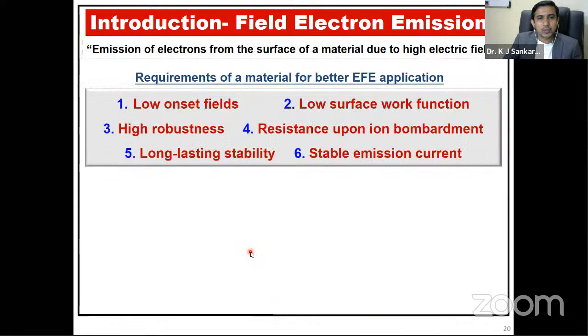To be a very good field electron emission cathode material, here I list out some of the requirements of a material. The material should have a low onset field, that is the low turn-on field, and it should have a low surface work function, high robustness, resistance upon ion bombardment, long lasting stability, and stable emission current. Based on these requirements of a material, we can utilize this material in field electron emission.